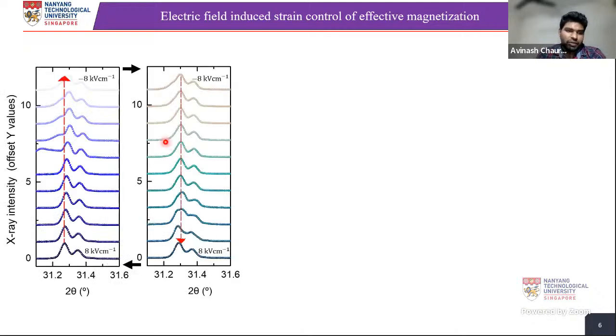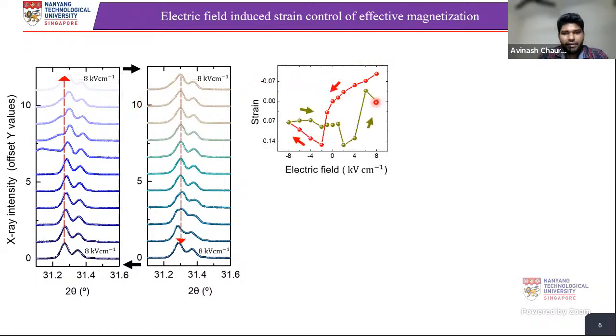First we did an X-ray diffraction measurement by applying the electric field on the device. What we see is that by applying the electric field, there is a shift in the X-ray diffraction pattern. This clearly shows that there is a strain in the device when we apply the electric field. Further, we calculated the strain using this spectra, and we found that by cyclic sweep of the electric field, it forms a butterfly loop. Now we wanted to see how this strain, which is due to the PMN-PT layer, will affect the magnetization of the adjacent ferromagnet layer.